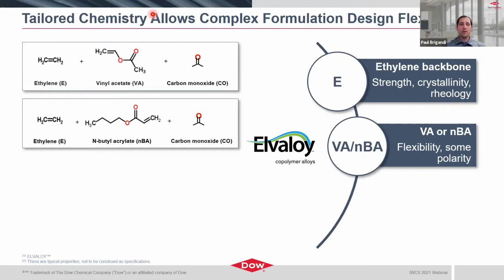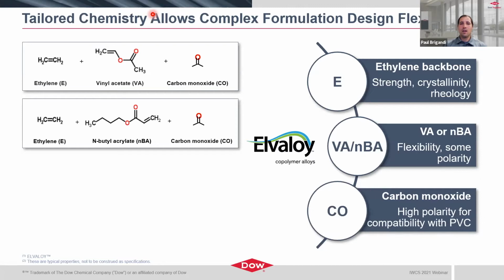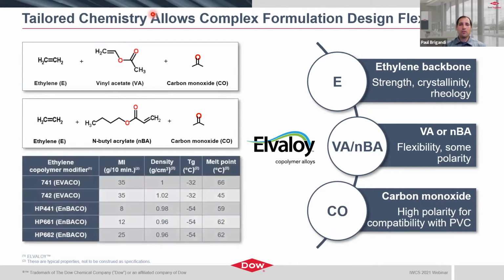And the last component is carbon monoxide. So we actually add this monomer in to impart even higher polarity, which is really going to dictate the compatibility with the PVC resin. So these terpolymers, so three monomers creating the terpolymer, are going to be used throughout the talk. And here I just give you a table of some of those terpolymers and their properties. You'll see them in some of the compositions that we actually tested, but also throughout the literature.